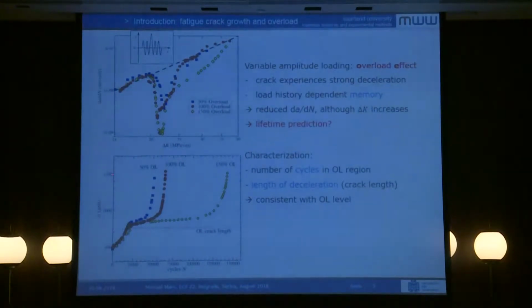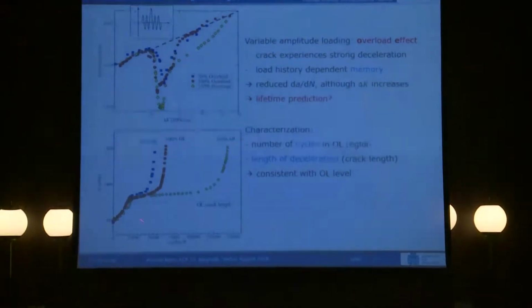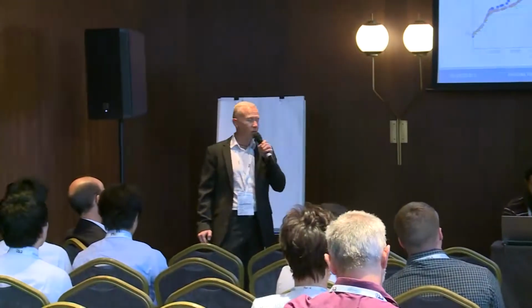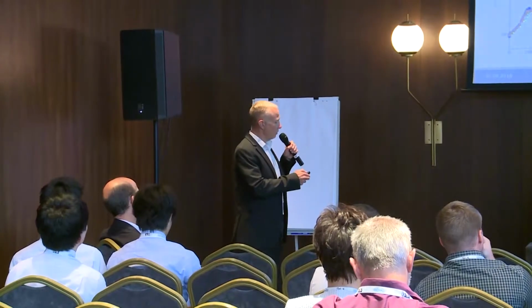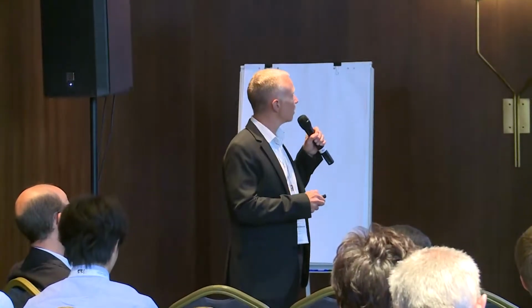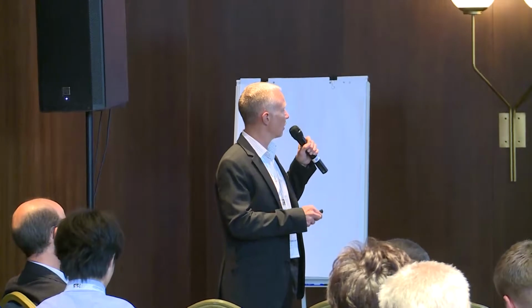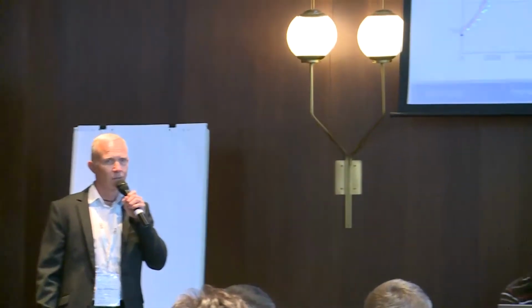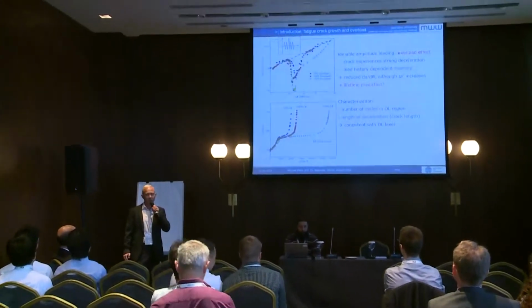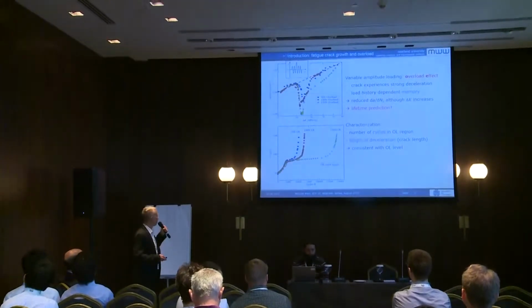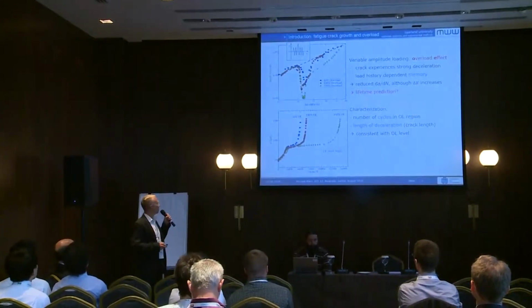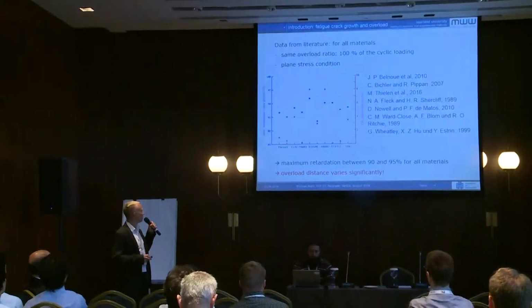Maybe if 1.5 millimeter crack length would be fracture of your specimen, then you would expect it without the overload after 25,000 cycles, and with the heaviest overload here, in this case 150% overload, you have fracture after more than 125,000 cycles, which is 5 times more than the expected lifetime without the overload. And this is what we investigated now a little bit more in detail.